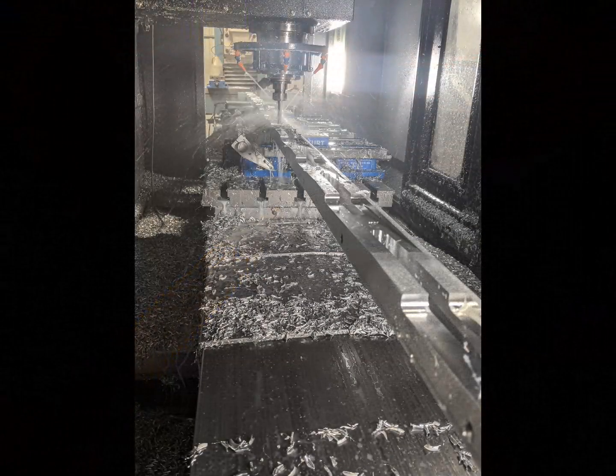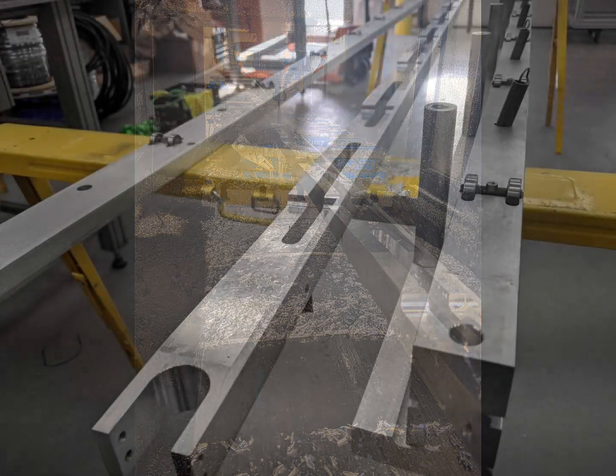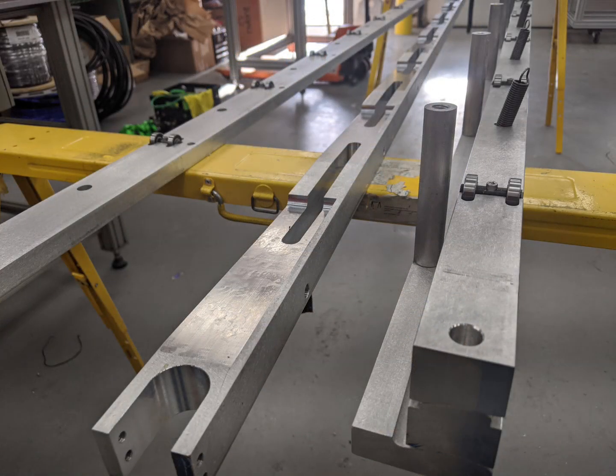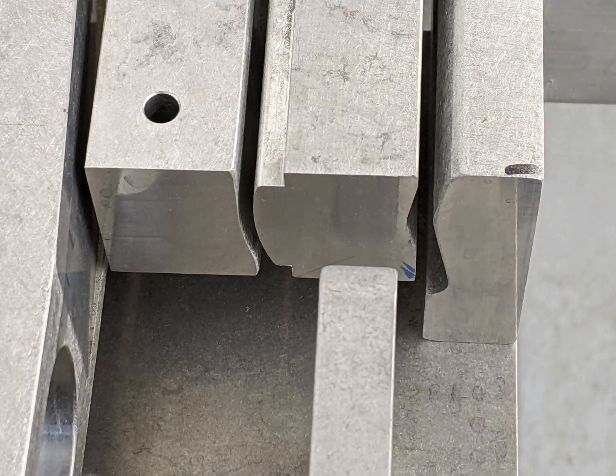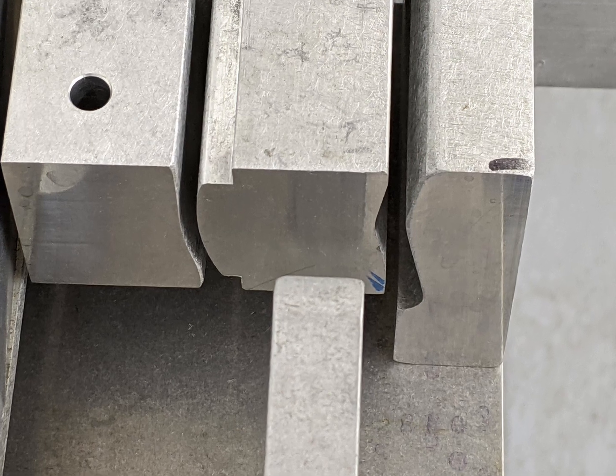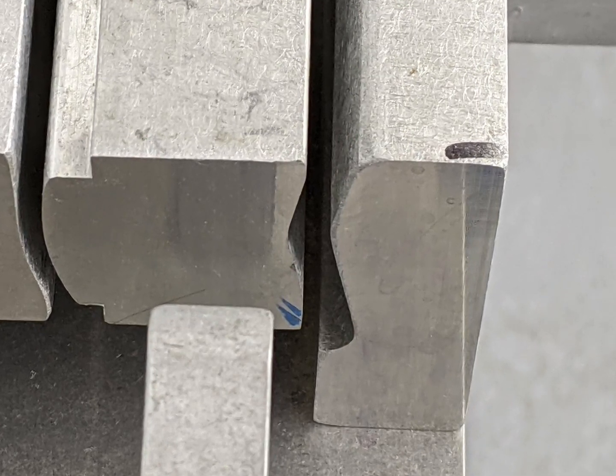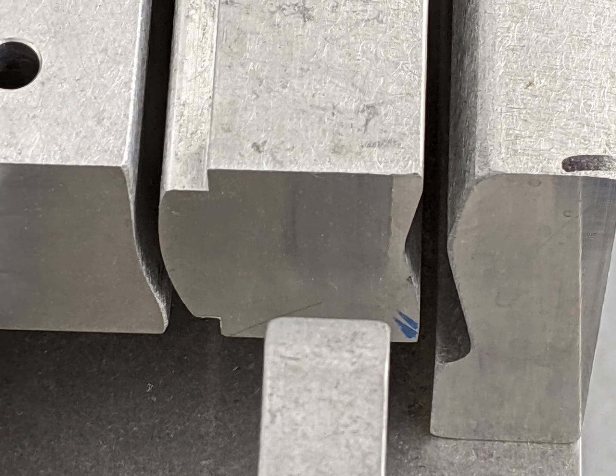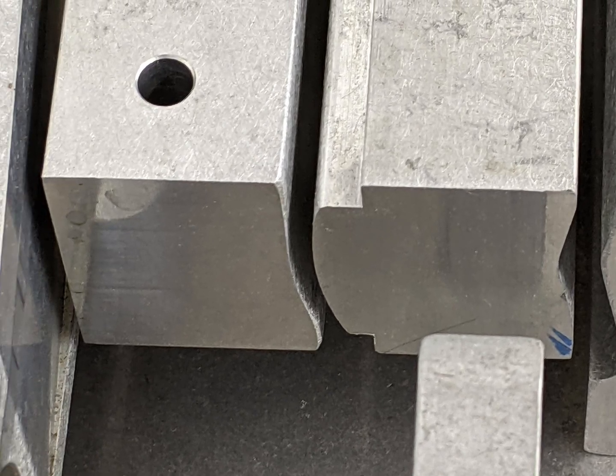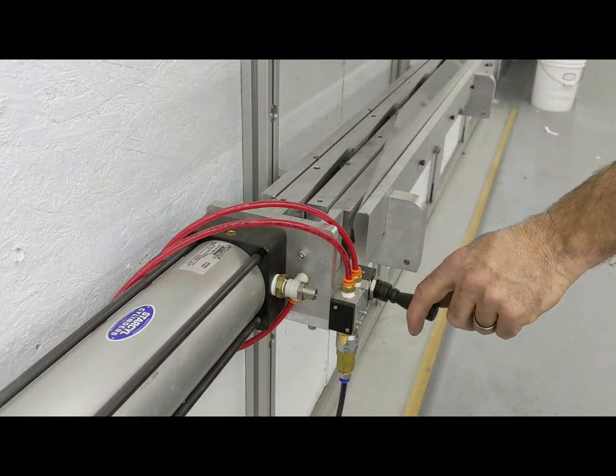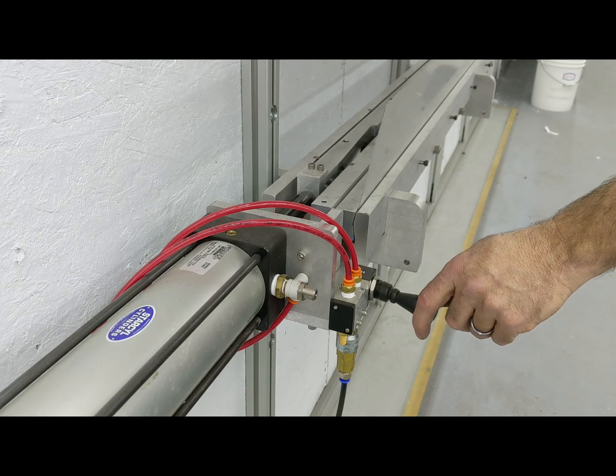To remedy this, we created our own custom 12-foot long sheet metal brake. All parts were built in-house. In this picture here, you can see the two zones. This zone here is for doing the reflex on the back trailing edge of the top skin. And this zone here is for making that small tweak to the top skin to eliminate that high pressure zone I just mentioned and get that smooth transfer. Simple cycle, tweaks the part.